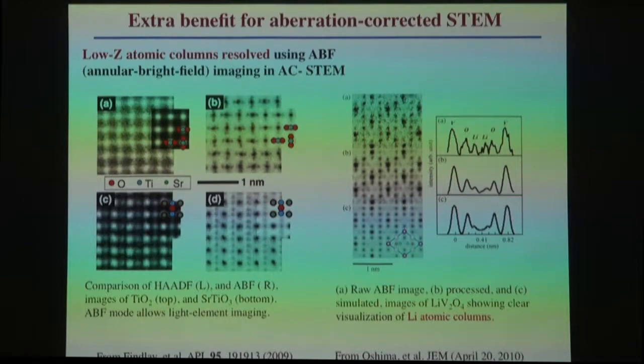And in this case, we have strontium titanate, and you can see the strontium and the titaniums, and we can also see the oxygen atom columns here. Very surprising. Here we are looking at lithium, getting down lower in the periodic table, lithium vanadium oxide. In this particular case, there's the experimental image, a bit of smoothing, and here's a calculation, and here's the structural model. The important thing for us here is that the intensity of the image has much less dependence on Z, and so it's possible to get vanadium, oxygen, and lithium visible all at the same time.